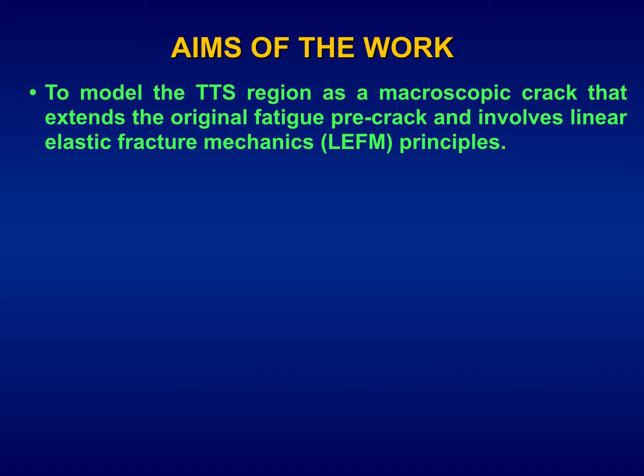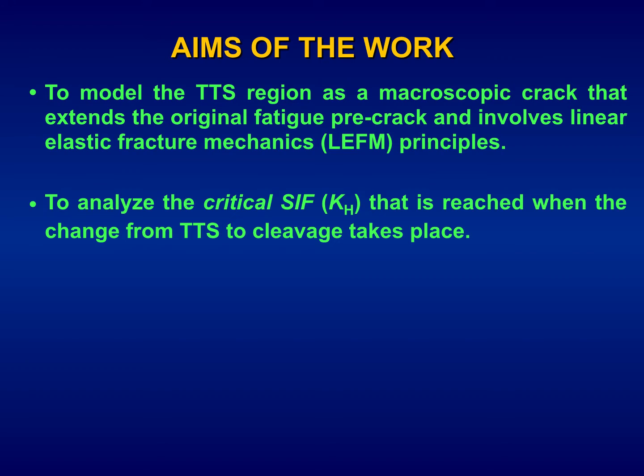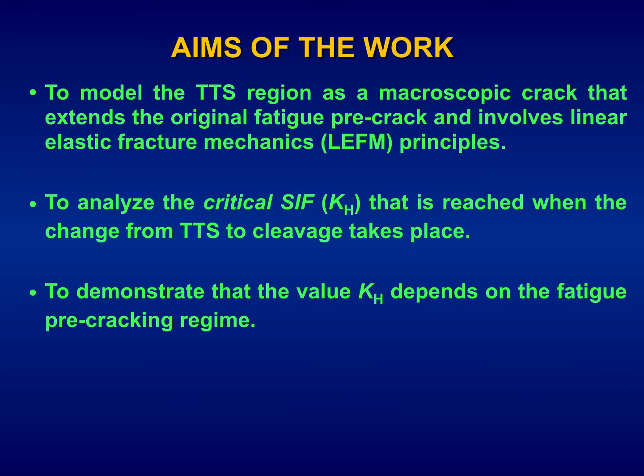The aim of the work is to model the TTS region as a macroscopic crack that extends the original fatigue pre-crack and involves linear elastic fracture mechanics principles, to analyze the critical stress intensity factor, KH, that is reached when the change from TTS to cleavage takes place.